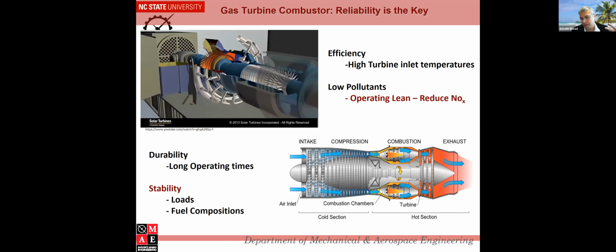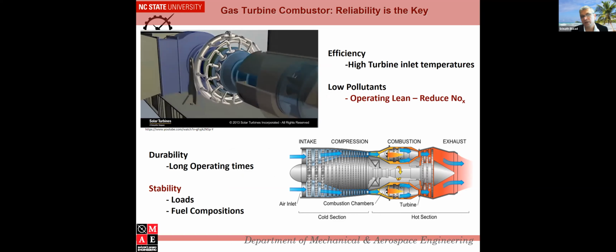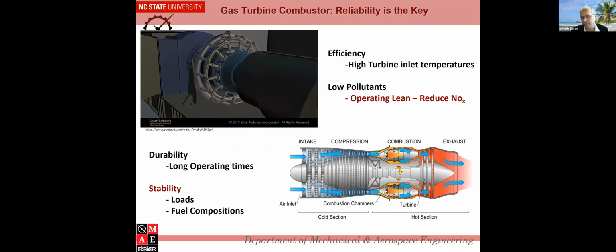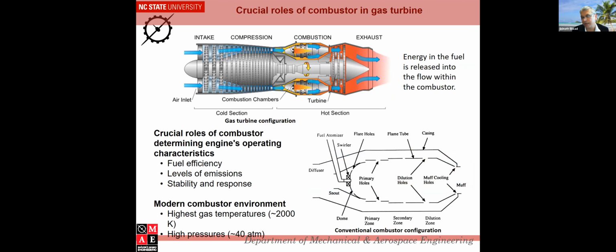and less fuel to improve the combustion at a lower equivalence ratio, so that you still get the temperature that you want, but you cannot use much cooling for the combustors. That means when you cannot use cooling, you need to know the heat transfer very effectively. In the past, the cooling design used to be like this, where about 40% of the air would come through the primary combustion zone, and the rest of the air would come in through these sleeves to help cool this surface and also reduce the temperature. So here you would have a very rich burning flame, very high temperature, upwards of 3000 Fahrenheit.